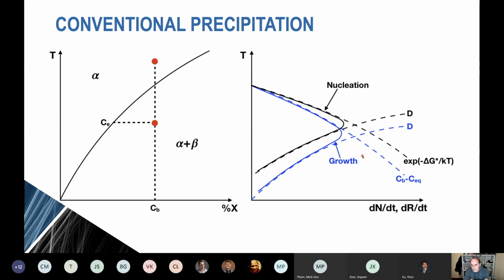The second important point I want to make is that the intermediate temperatures that we choose that give the maximums in the transformation rates are very similar for both nucleation and growth. And what this means is that it forms a constraint on the combinations, or let's say the competition between nucleation and growth, and that provides a constraint around the combinations of particle number and size that we can achieve experimentally. And so that has an influence on the types of mechanical properties we can develop.